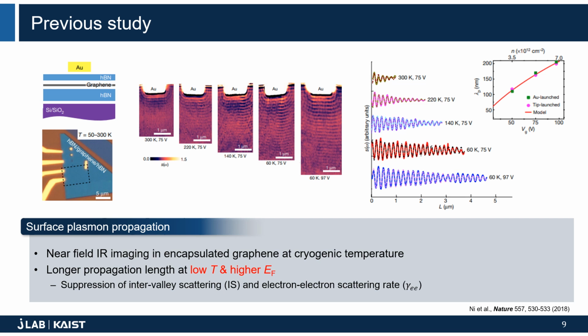The study quantified the dynamics of the quasi-particles that underpin the plasmon propagation. However, in this study, we aim to investigate the behavior of graphene plasmons as a function of temperature in a more conventional setup by performing far-field measurement with the hBN encapsulation layer removed, which allows us to study the temperature dependence dynamics in a simplified system.